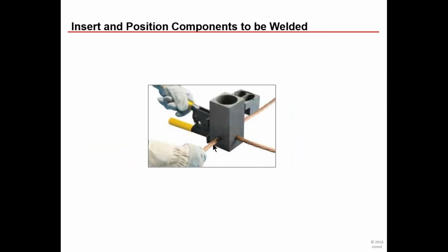Another important part for a quality weld is to make sure your positioning of your conductors is correct. If you have some excessive bends, it may not allow the mold to close properly. If it doesn't, you may have some blowouts of the weld material. These clamps are made so that you know it's fully sealed because the clamp does a little pop at the end where it has a groove where it seats. If you don't feel that, where it almost has a little hiccup or a bump as you close it, then it's not closed all the way and it's not tight, and you could have issues. So it's imperative that your conductors are set properly and you close the clamp all the way.